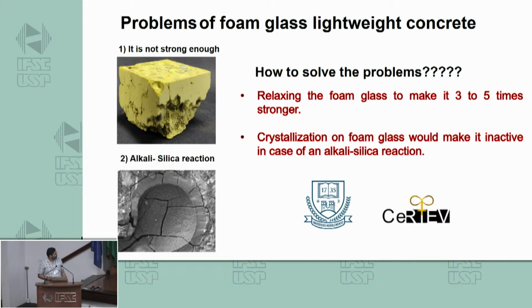Foam glass has some problems for use in concrete. The first one is that it's not strong enough to make a structural concrete. And the second one is the alkali-silica reaction that takes place between foam glass, because of its amorphous nature, and the cement mortar. So I'm here to learn how to make foam glass relax, to increase its strength, and how to crystallize it to avoid the alkali-silica reaction between cement and foam glass granules. Thank you very much.